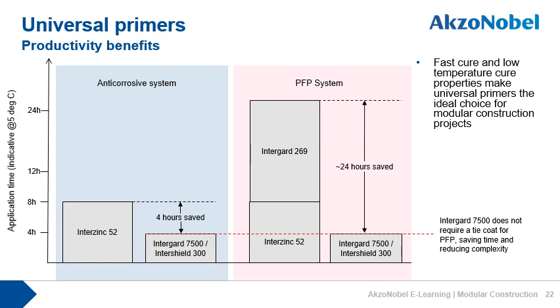The effect is magnified for fireproofed areas, and this is because the traditional approach would require an application of a tie coat, meaning that you would need more than 24 hours between the primer application and the fireproofing. In contrast, with a product such as Intergard 7500 or Intershield 300, the fireproofing can take place in the same shift as the primer application. And that saves a massive amount of time especially in modular construction.